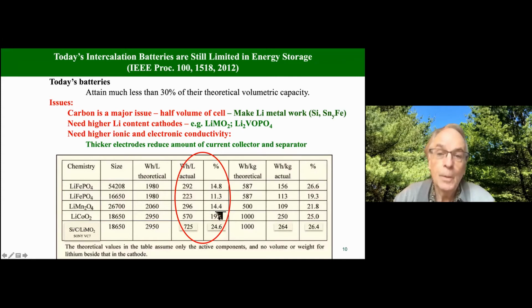So there's a huge opportunity to increase the stored energy density, and I'm part of the Battery 500 consortium, and our goal is to get these numbers here in this column up to 500, and I'll show you data in a few minutes. To do this, we've essentially got to eliminate most of the graphitic carbon. We've got to make an alternative work. We've got to use more of the lithium in the cathode materials. As Jeff has shown, this is going to be really challenging for the layered oxides. And this opens up the opportunity for the phosphates, which are safer and more stable.